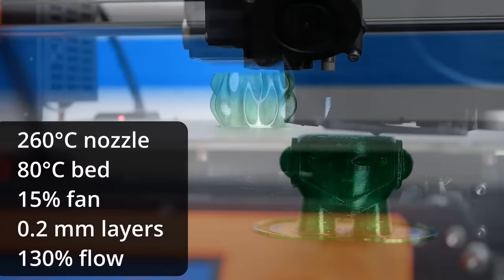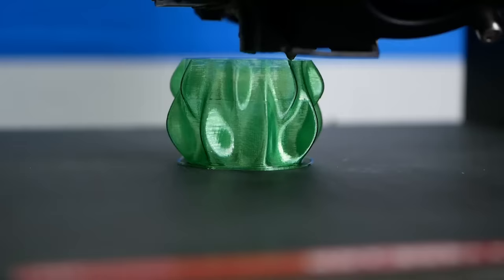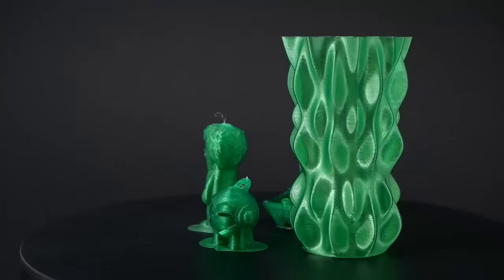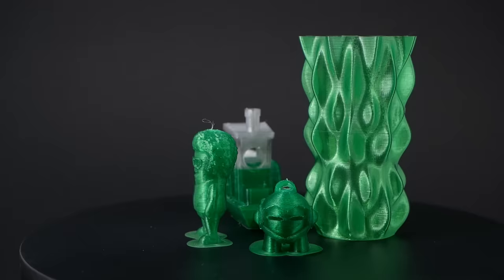Due to the difference in diameter, I set the flow to 130% which was almost spot on. I didn't have a lot of material, so the number and size of prints were limited.